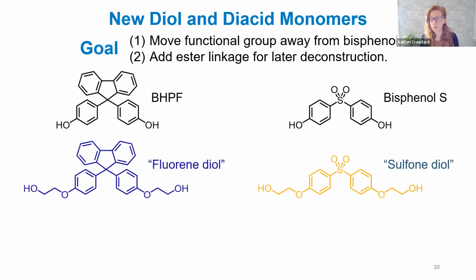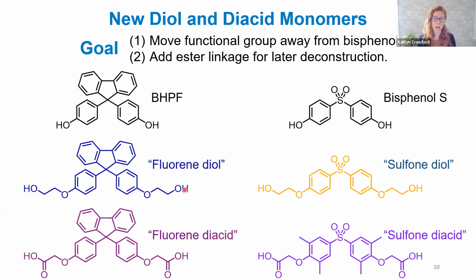So the first thing we did was we took the fluorene and sulfone diol derivatives, and we extended the hydroxyl group away from the aromatic ring, just as I suggested. And then in addition to making these diol derivatives, we also made diacid derivatives with a fluorene diacid and sulfone diacid. And the reason why we did this is because we can polymerize the materials together by joining diol groups and diacids.